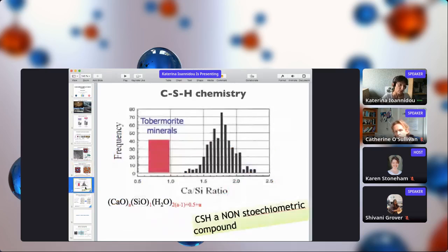But let's move back to the atomistic scale, and let's go back to where we said that calcium silicate hydrate is a non-stoichiometric compound. We have a very nice mineral called tobermorite, with a very specific, nice crystalline structure, but this is very rare. We only find it in nature after waiting many years. In the cement we usually have in our houses, which solidifies within 10 hours, we don't have a fixed stoichiometry, but a whole distribution of this material with different calcium over silica ratio that spans from 1 to 2.5.